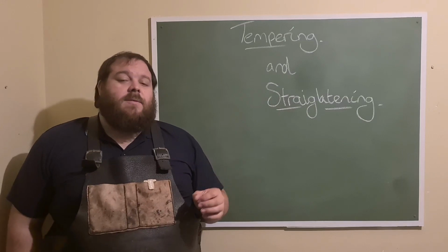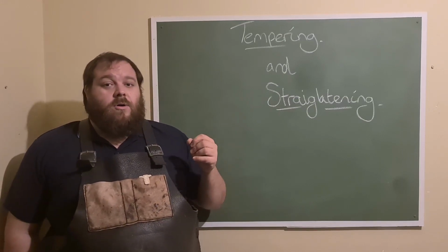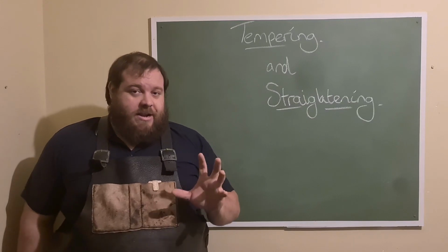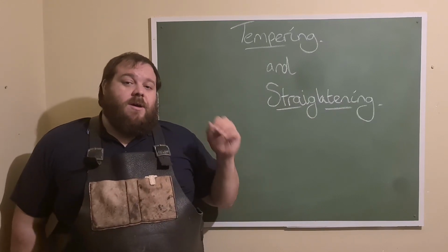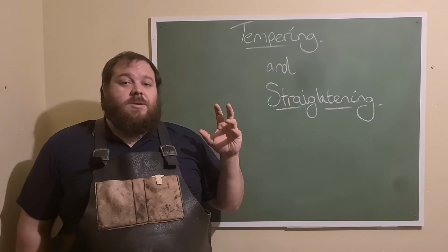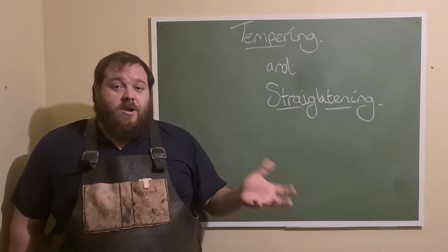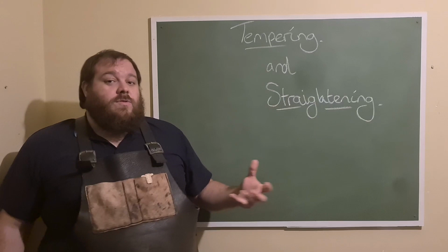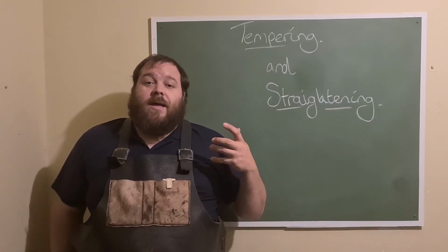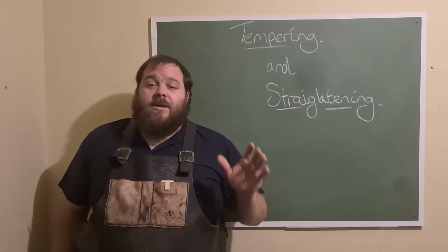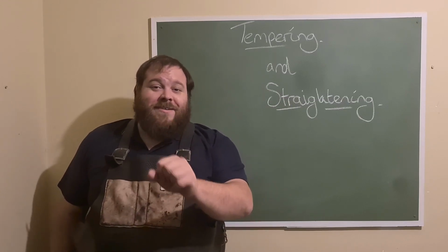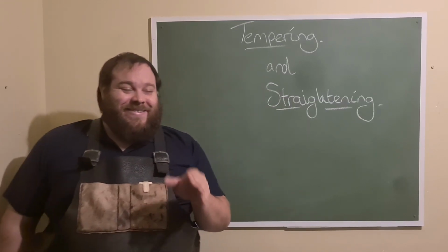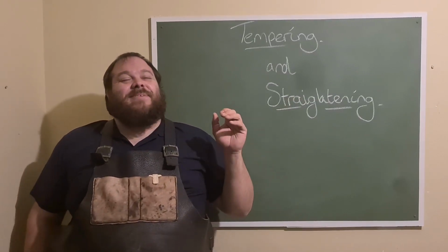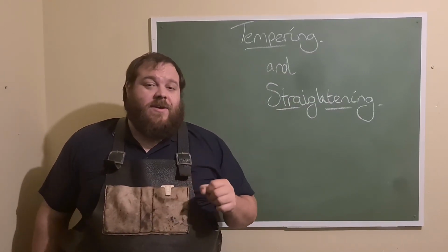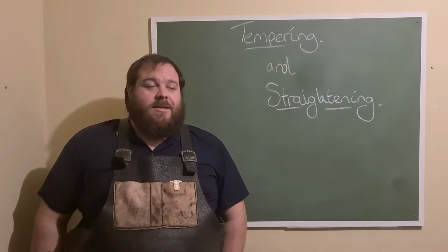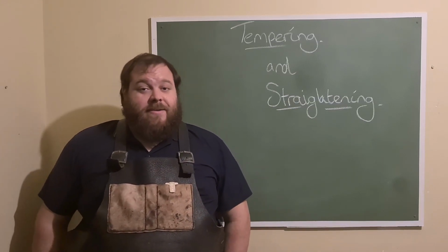You can lightly beat the blade with a brass hammer or even a wooden hammer, very gently, not aggressively. But because the spine section is softened, it will actually bend and straighten on its own. So you may not need to use a 3-point straightening jig or anything like that, because you'll be able to straighten freehand at the anvil after your first temper cycle. Do not try it right after quench, please. But yeah, temper first, and then you can beat the blade straight, rather than having to go to a 3-point jig or anything like that, and potentially snapping your blade in half.